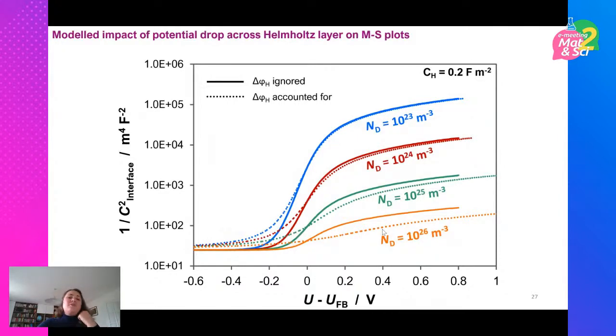I hope this summarizes why, in addition to actually working out the capacitance values from impedance measurements, interpreting the data can be associated with a lot of error if you don't actually have information about your semiconductor, like accurately knowing the doping density, which if you were to get it from the slope of these plots would be incorrect. So it has to be determined using some other methods.